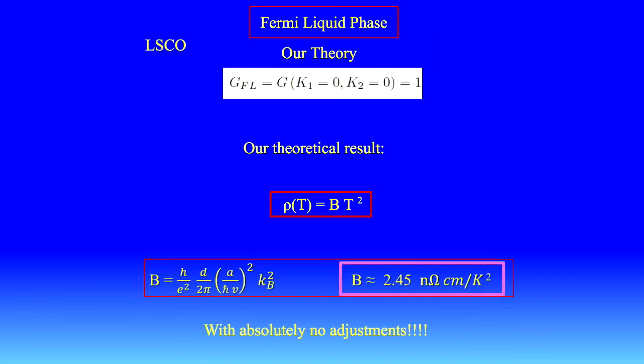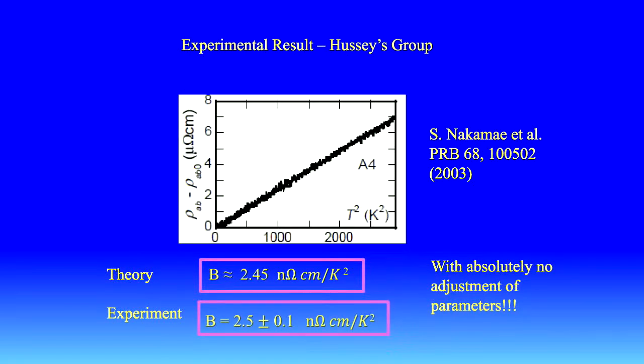Fermi liquid phase. This is one of the most spectacular results. In the Fermi liquid phase, you have G equal to 1, so the resistivity is BT squared, which is the correct expression for a Fermi liquid, where B is given by this, and we calculate it without adjusting anything. Now, a measurement of this by Hussey's group, Nigel Hussey, a colleague of Michael Berry in Bristol, obtained this, notice that this is resistivity versus T squared. So this slope gives this. And this is our theoretical result without adjusting anything.